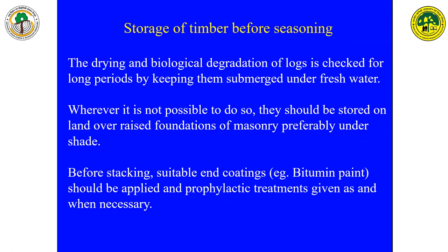immediately after the logging operation in the forest, we should apply bitumen paint, which is black colour paint, readily available from Shalimar Paints or Asian Paints, these big companies. We should purchase and apply it onto both the cross sections of each log. This will seal the cut ends of both the cross sections, and water will not be allowed to come in very fast. So ultimately cracks will not develop.